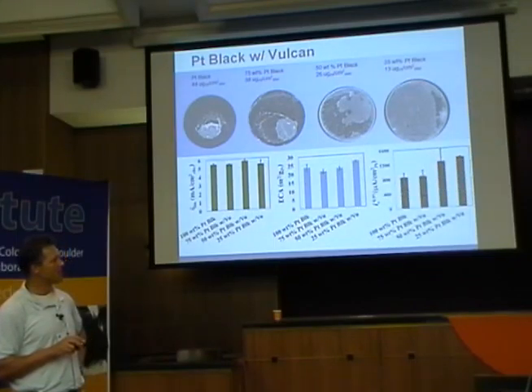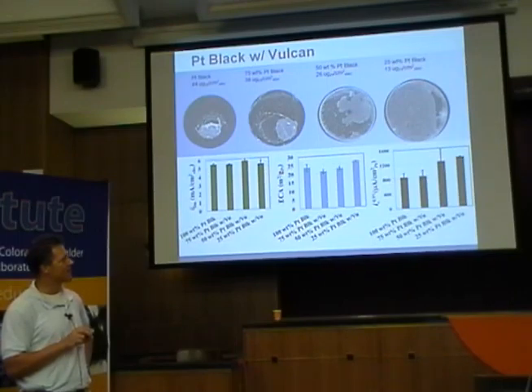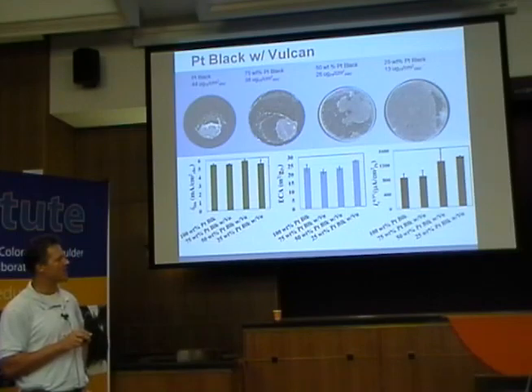The real issue comes when you see how well they're performing, and you can see that here, because you have so much of this platinum meshed up together, you're not using it as effectively as this one over here or this one over here. And so these give you much lower specific activities where these give you much higher specific activities. So most people would only have looked at this case and assumed that everything was fine because they had a good limiting current and they have a high surface area.